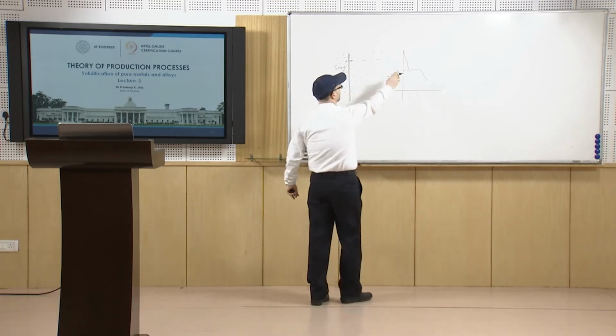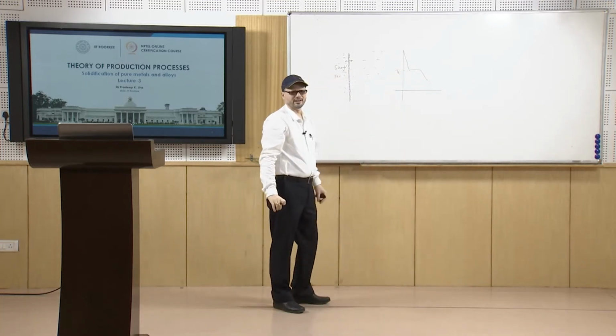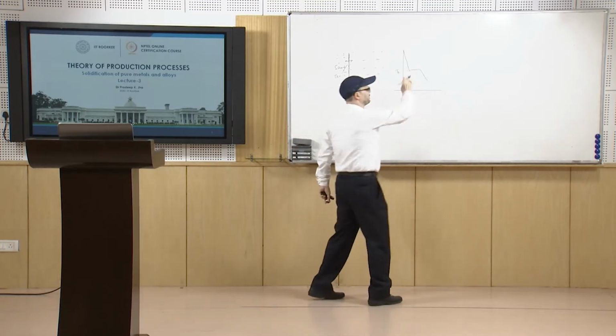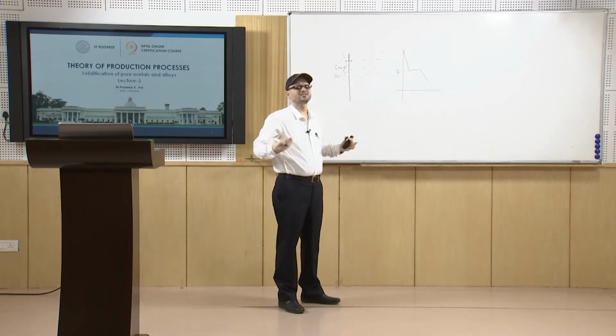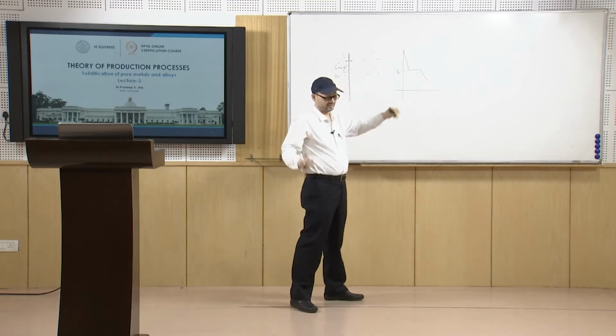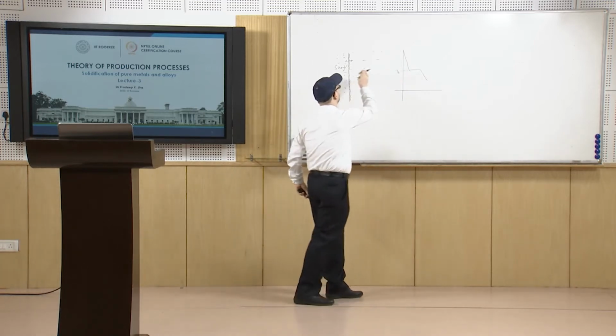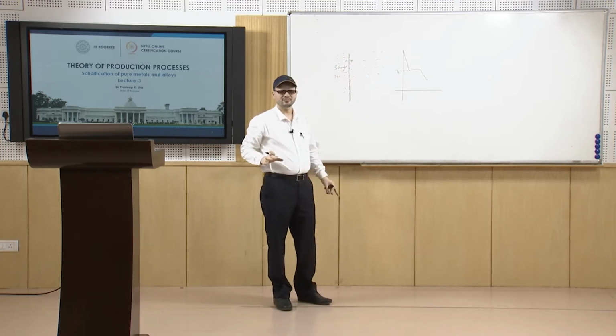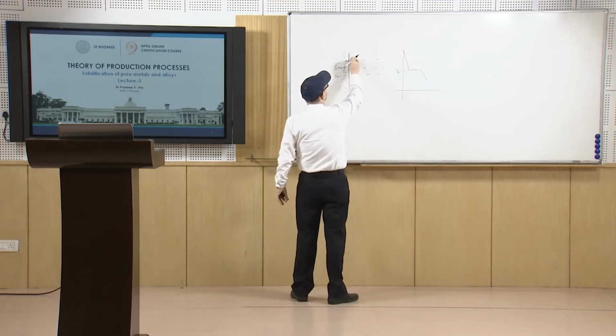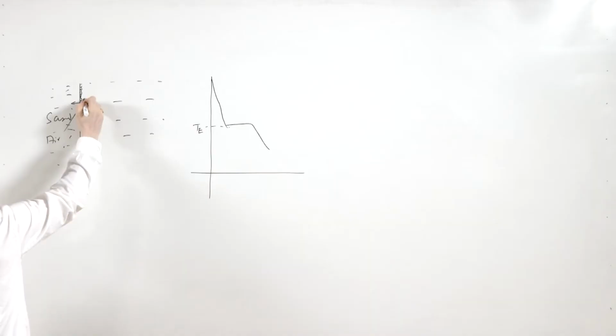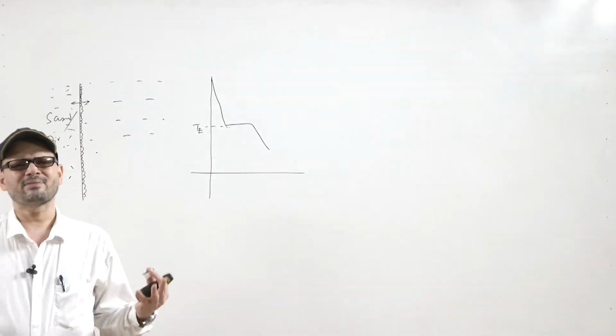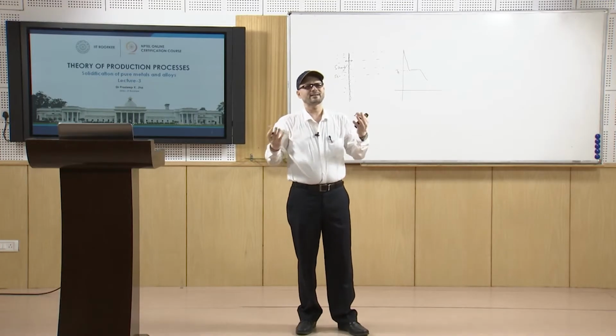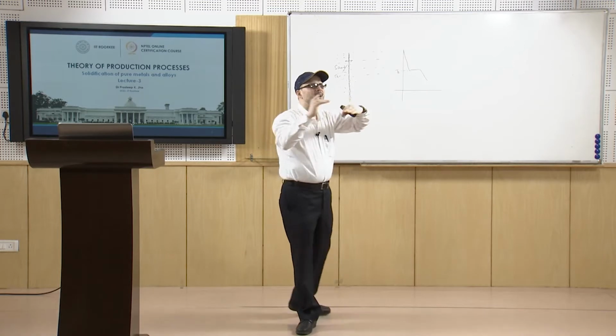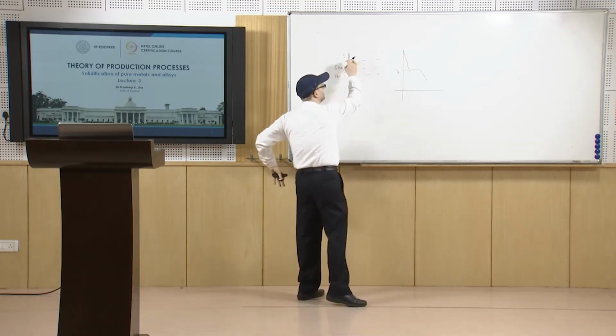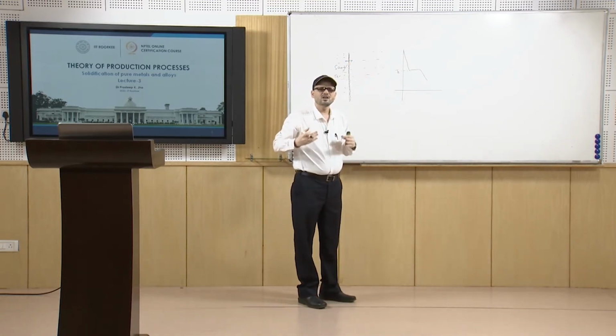Suppose this temperature is 800 degrees centigrade at which the solidification has to start. Now, let us say for copper it is 1083 degrees centigrade. So, suppose at 1083 degrees centigrade the nucleation has started. What happens in this zone also, here the probable temperature will be close to 1085 or maybe 1084, 1086 or so, which will basically come towards 1083, so that it will also start solidifying.